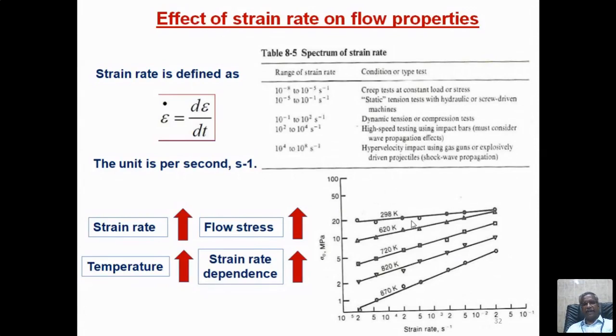So for strain, there is no unit. For time, you have the unit of second, 1 second. So 1 by S is S power minus 1. So what is the effect of strain rate? If you use a higher strain rate, you have a higher flow stress; flow stress will be very high. Higher strain rate, definitely the flow stress will be high. And if you raise the temperature, again it is strain rate dependent. You can see this graph: stress versus strain rate for different temperatures. So strain rate dependence is a temperature dependent property.